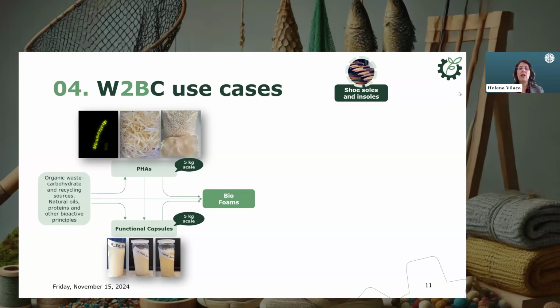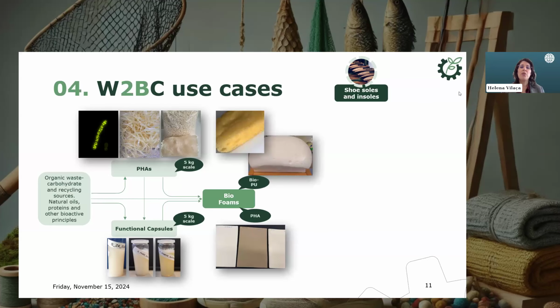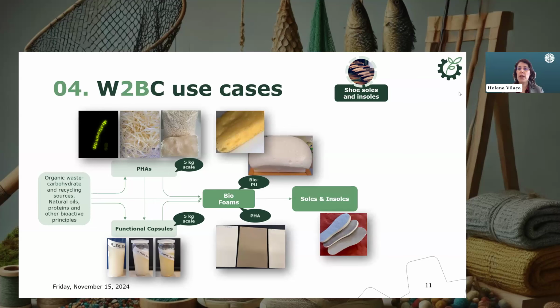Combining the PHAs and also the capsules, we have produced bio-based foams. If coming from the PHAs, we produce PHA-based foams. We have here some pictures of the foams with different percentages of PHAs and with different hardness levels. But we have also been able to come in, for example, from biopolyols that are available, and produce also bio-based polyurethane foams. We are now in the phase of developing the soles and insoles using these foams. We have here an example of a polyurethane-based foam that was grown, let's say so, directly on a textile substrate, so we obtain a final insole.